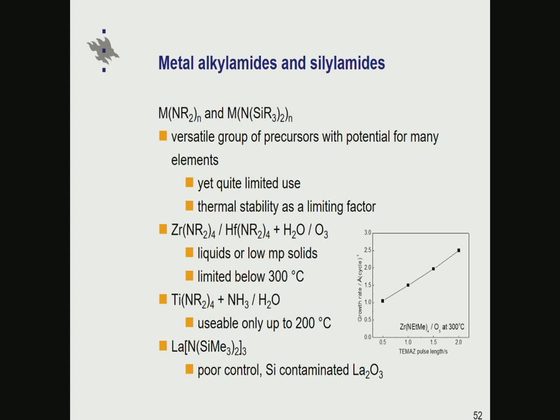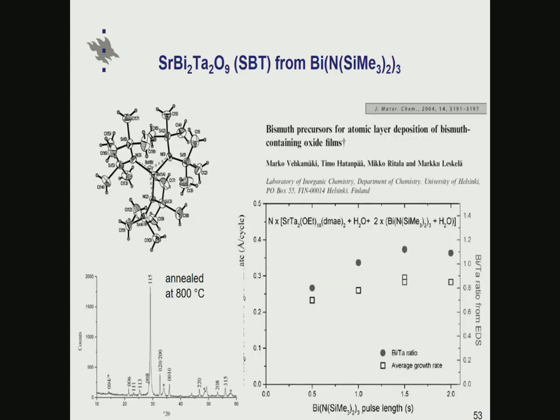We have used this, for example, for lanthanum, but the problem in the case of silyl amides is that silicon can quite easily also get incorporated into the films. And one example of using silyl amides was for making various kinds of bismuth-containing films, and there the key was to use this as a ligand for bismuth.